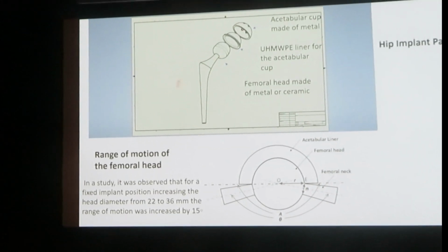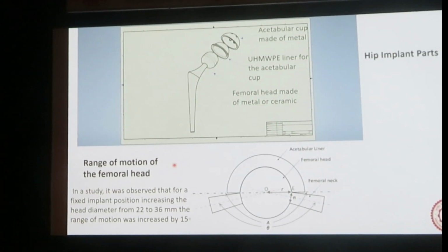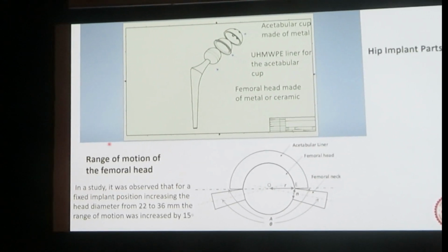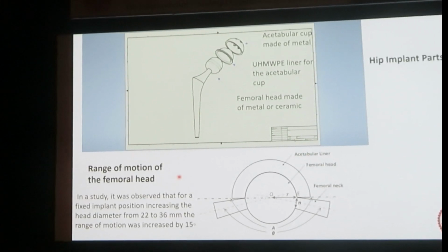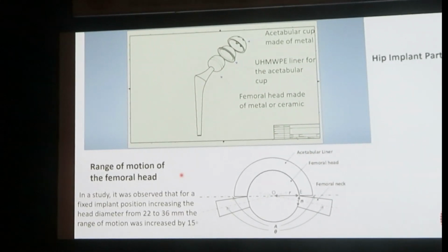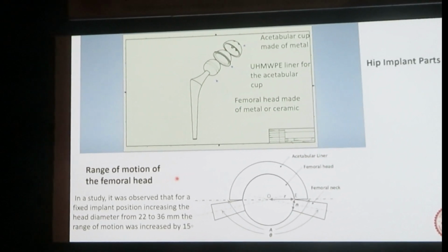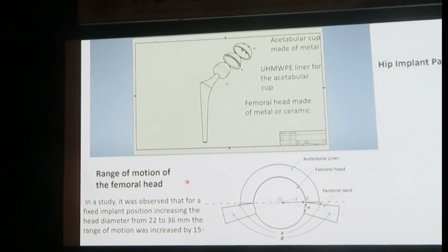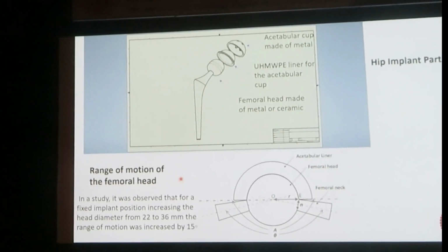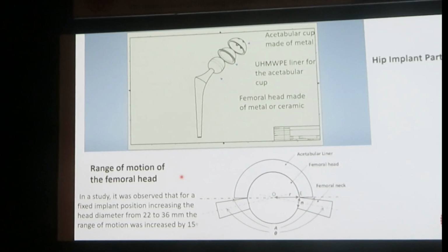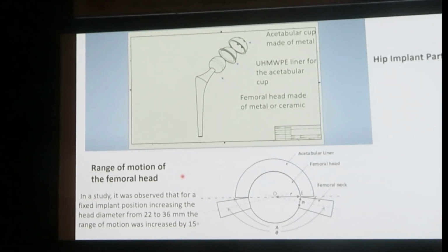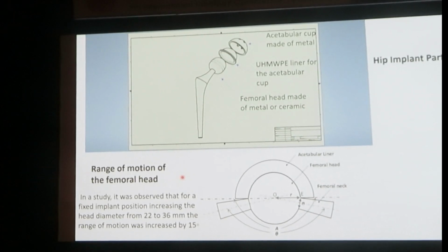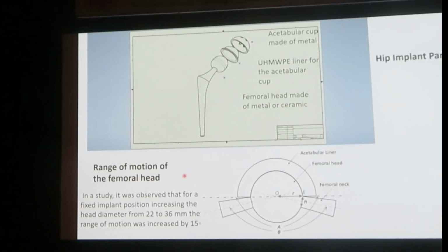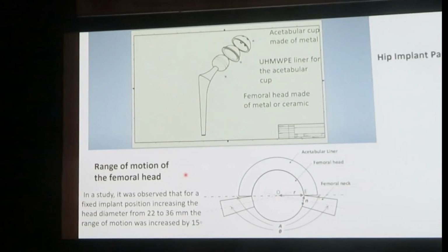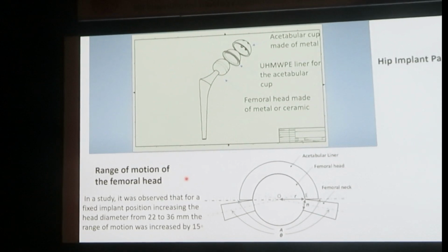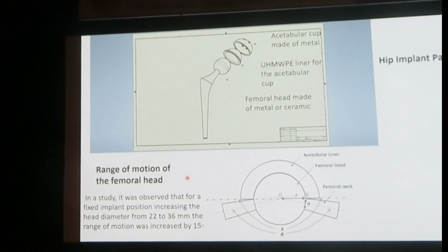So this is the schematic, and other than the wear problem, there is another problem, which is the range of motion of the femoral head. Having a good range of motion for the femoral head will lead to better stability. That means the chance of dislocation can be reduced if you have good range of motion. And a good range of motion can be achieved if you have a thinner liner, not a thicker liner, because the space in the pelvis is limited. So you can say the outer diameter is fixed. We can only play with the inner diameter, because the outer diameter is fixed by the pelvic size. The inner diameter can be increased.